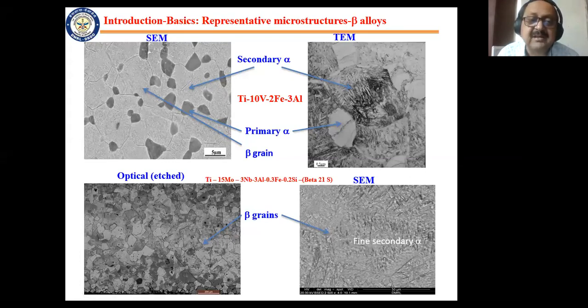So all these beta alloys have much higher strength as compared to Ti-6Al-4V and others. But in these alloys, after you have alpha plus beta deformed, you solution treat in the alpha plus beta regime, and then you have to age it to get this. In Ti-6Al-4V, if you deform, solution treat, and cool it, you will get this precipitation of the alpha. But in this, not. So that is the difference between beta alloys and the alpha plus beta alloy.